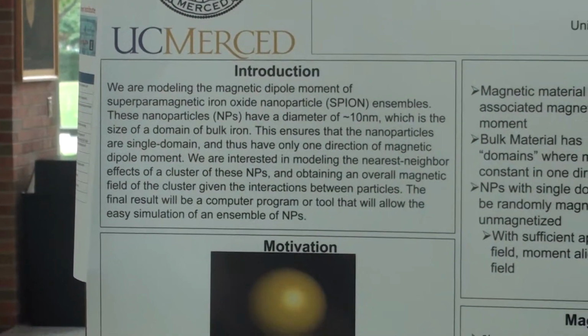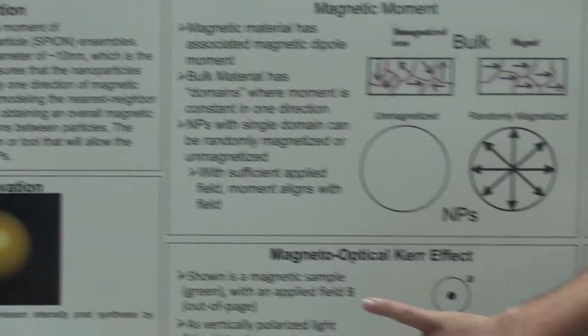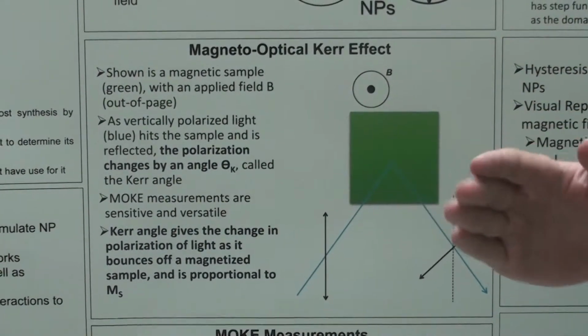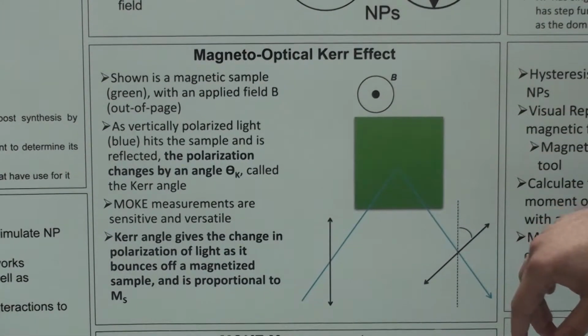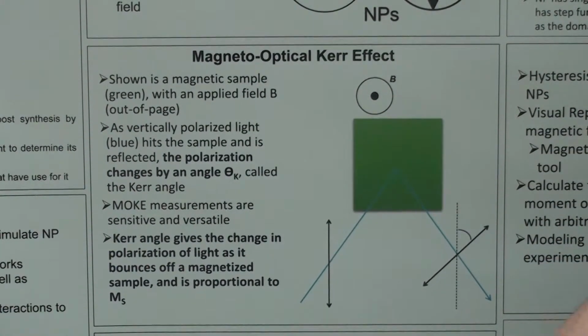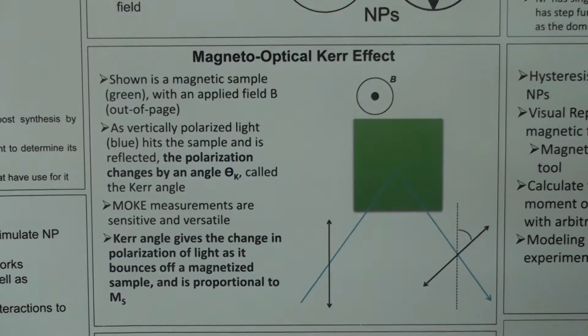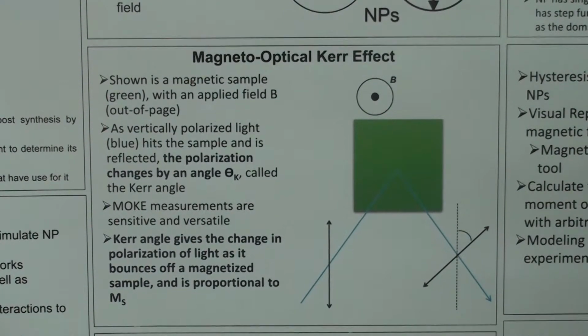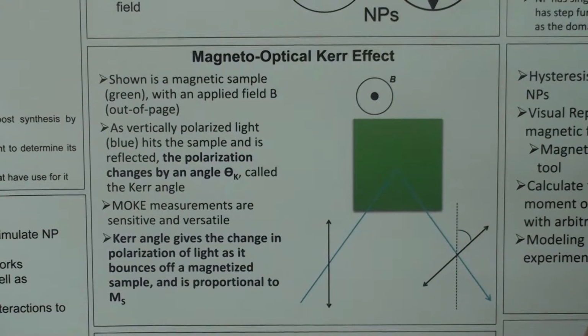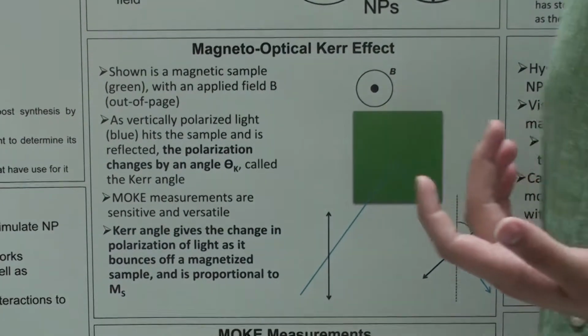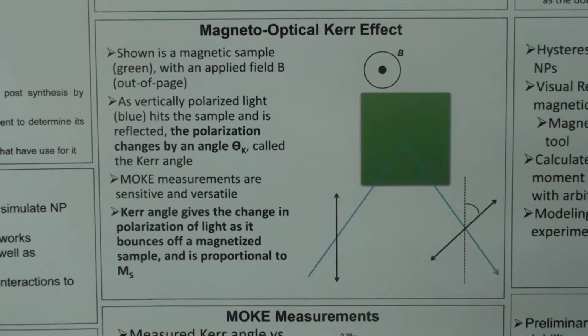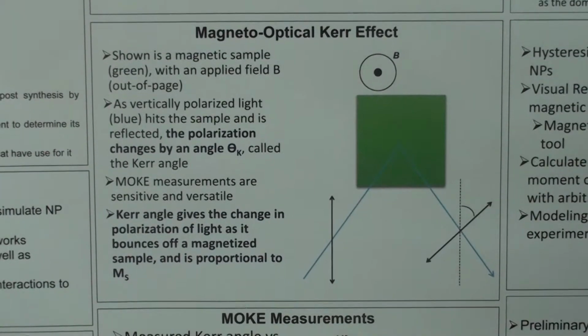Now, being able to simulate this would be very useful in that you can use it to deconvolute certain optical experiments, like the magneto-optical Kerr effect, in which you bounce vertically polarized light off a magnetized sample, and the polarization of the light changes by a certain angle. This angle is very small, like a microradian, but we can still measure it. And this angle is proportional to the total magnetization of the sample.